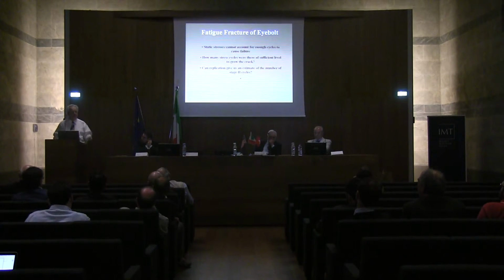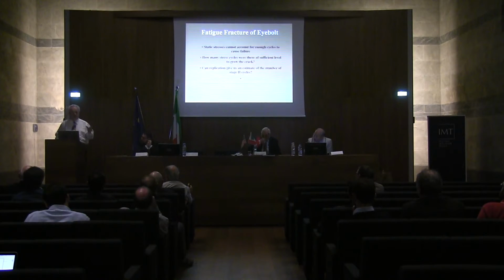Now, if any of you have done this kind of work, you know that in body-centered cubic metals, such as iron, fatigue striations are irregular in appearance. They're not uniform, and they're difficult to measure. Face-centered cubic metals are much more ductile than body-centered cubic, because they have close-packed planes and close-packed directions, whereas in a body-centered cubic, you only have one close-packed direction, no close-packed planes. So in face-centered cubic metals, you have better-looking striations to make the measurement. So this is a tough analysis.